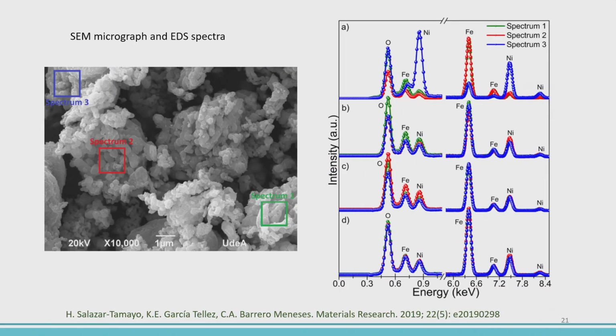Here we showed some SEM micrographs, and we took 3 zones for typical samples, this blue, red, and green. By the EDS spectra, we determined the qualitative chemical compositions in the 3 zones, and we notice that as the temperature increases, the zones become homogeneous in the distribution of the ions. It is very interesting because it is also in line with the previous interpretation of what can be happening with the temperature.